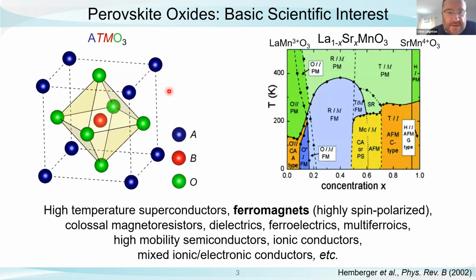Okay, so oxides, perovskites in particular, I'll spend a lot of time on. Probably many of you are familiar with this base perovskite structure. This is the undistorted cubic structure, where we put a transition metal in the center of this cubic unit cell. We have oxygen that forms an octahedral cage around that transition metal, and then on the corners of the cube, we put an alkaline earth or a rare earth material. The reason there's so much interest in these perovskites is really their very diverse electronic and magnetic properties. So if we put copper here on the B site, this is the basic structural unit that makes up high temperature cuprate superconductors. If we put cobalt or manganese, as I'll talk about today, we get ferromagnetism with high spin polarization. This structure also supports colossal magnetoresistance and then many types of multiferroics.